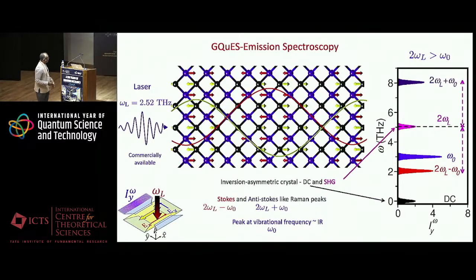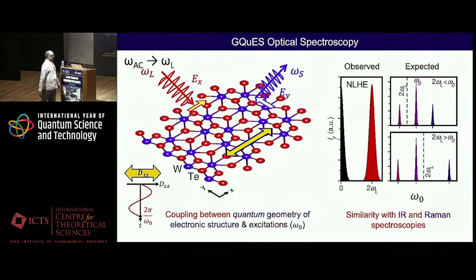You can also have another mode called emission spectroscopy, which means using terahertz frequencies. You shine terahertz light, which is commercially available, and measure the radiation emitted by this device with a perpendicularly polarized field as a function of frequency. You again get a set of peaks, shown here. You have 2 peaks associated with rectification, one at 0 and one at 2 times omega L if the Berry curvature dipole is non-zero. The other 3 peaks are linked to Stokes and anti-Stokes as indicated here, and the mode at the phonon frequency itself. Wonderful. So this is what our predictions are.